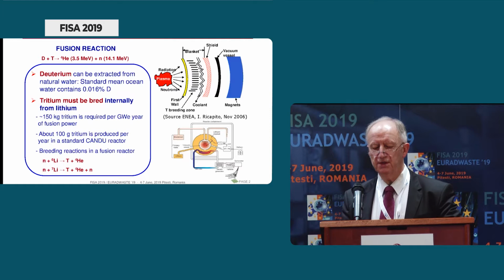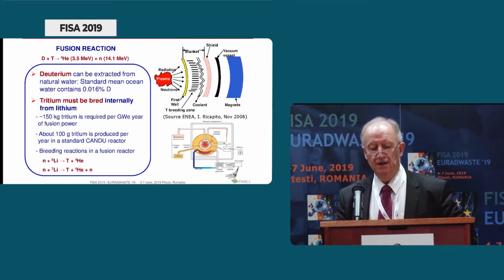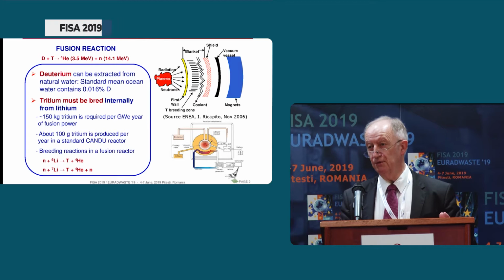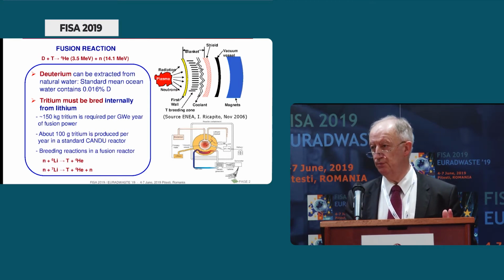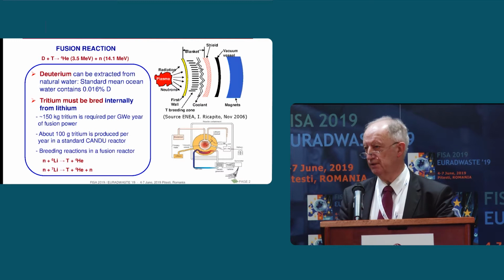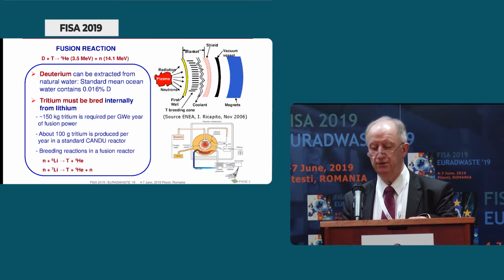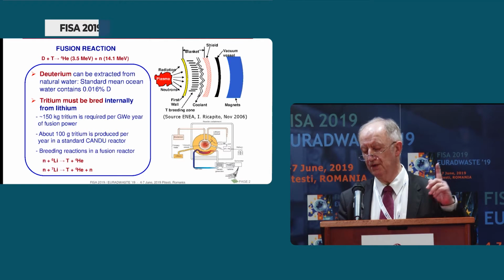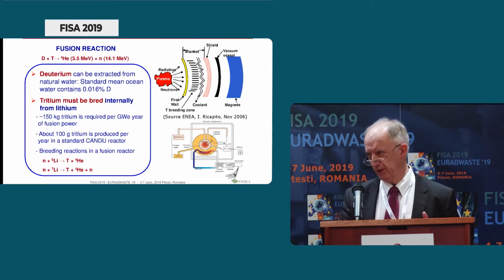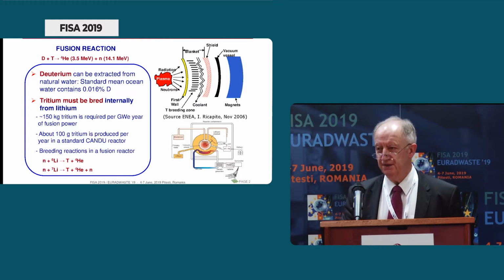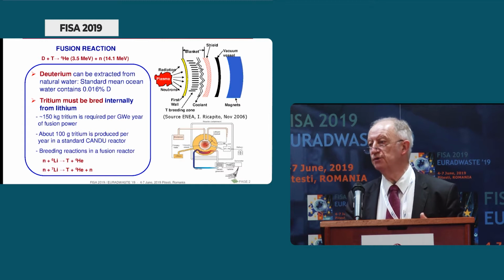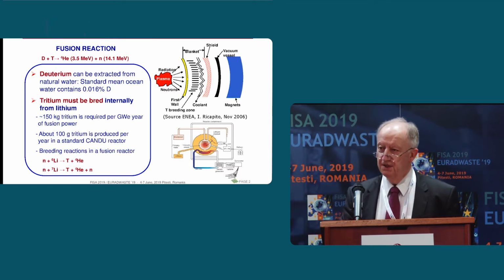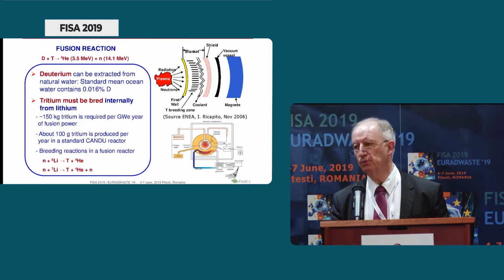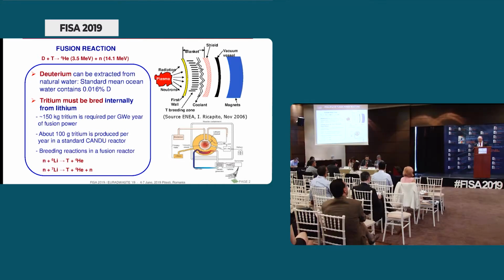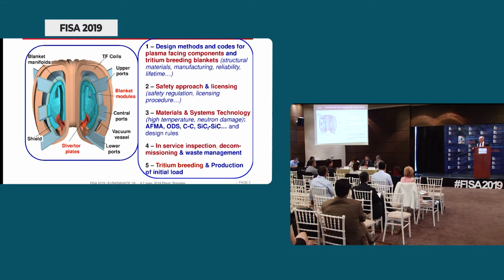Just to stress the importance of this tritium issue, a typical 1 gigawatt electric reactor would burn about half a kilogram of tritium per day, whereas a CANDU reactor, 600 megawatt electric, currently produces about 100 grams of tritium per year. And you see it is absolutely important that fusion reactors be autonomous in terms of tritium. Otherwise, the makeup that they would require would need a supporting fleet of fission reactors at least of the order of the fusion power that is installed.